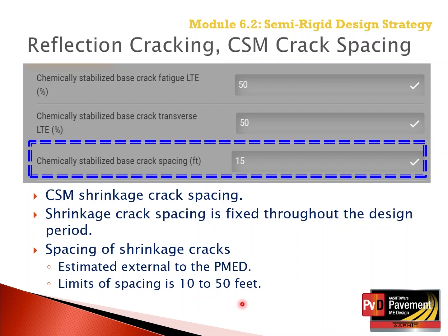the software. If it's a more severe type of cracking, with spacing much less than 10 feet, then the chemically stabilized layer can be simulated in the flexible pavement design strategy, but it is no longer considered an intact layer for semi-rigid pavements.